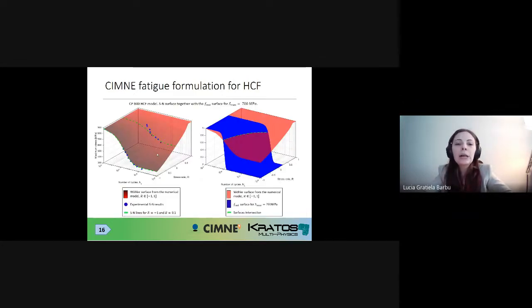And just to finish this part, I want to stress that we are not working with discrete, with isolated SN curves. When we are calibrating these materials and we are calibrating specific curves for specific reversion factors to experimental points, what we are actually doing is we are configuring this whole surface of the SN curve.